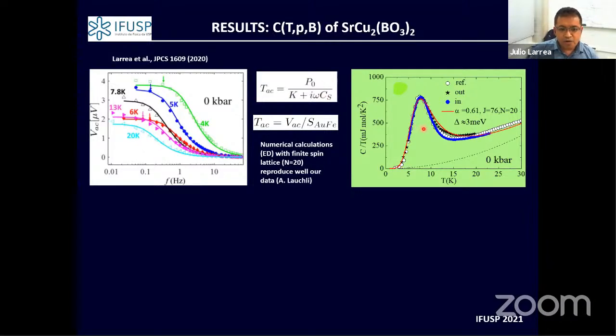On the other hand, if we compare with a reference measurement done more in an adiabatic condition, using the time relaxation technique, what we have seen is that our measurement coincides very well, in good agreement, giving us the confidence of the accuracy of our measurement to resolve a specific heat absolute value within an order of 5%.